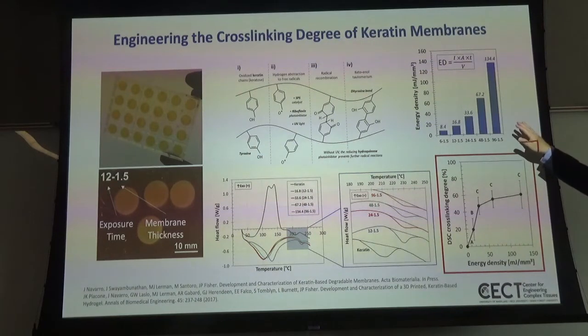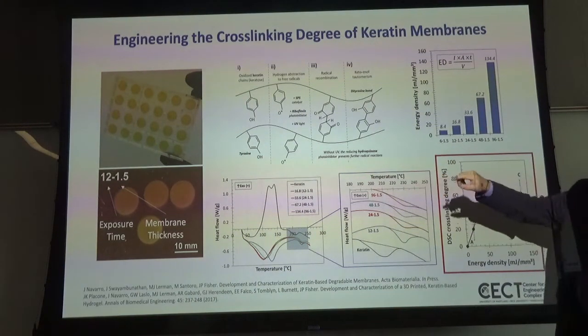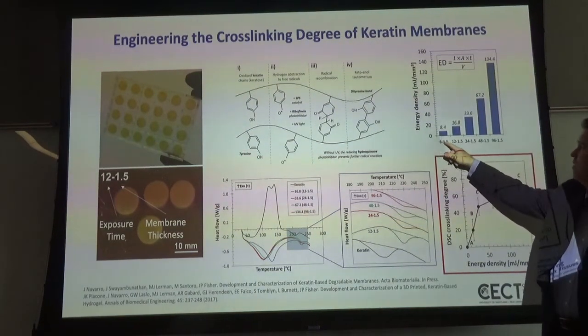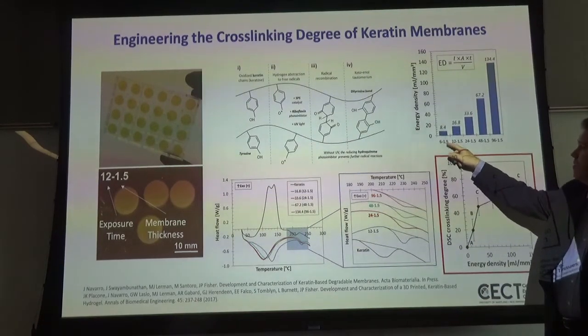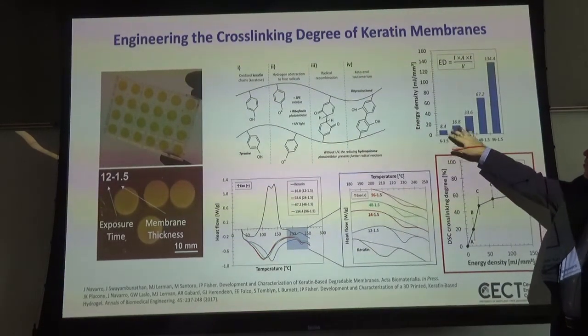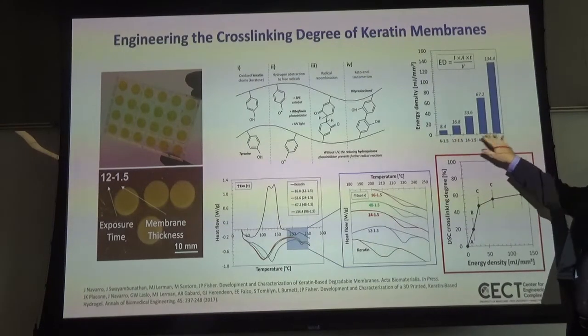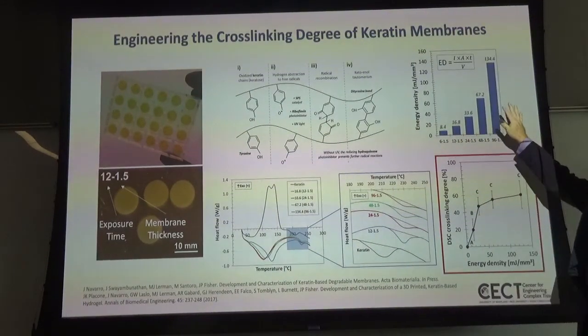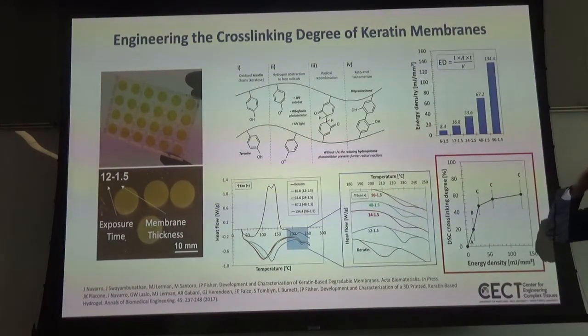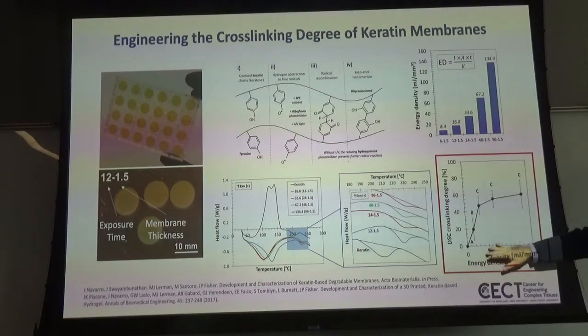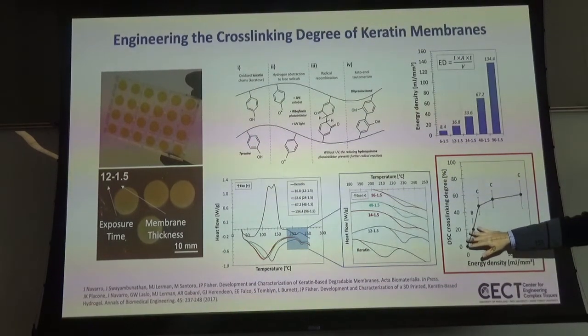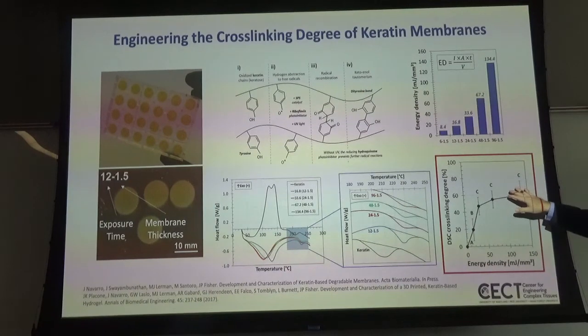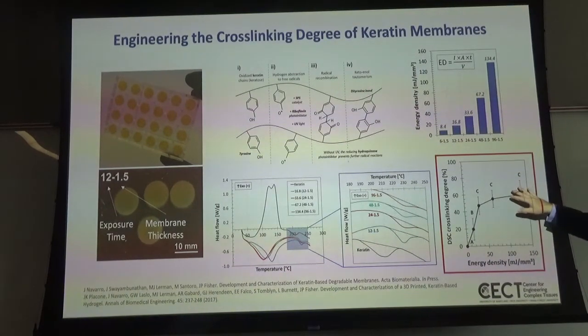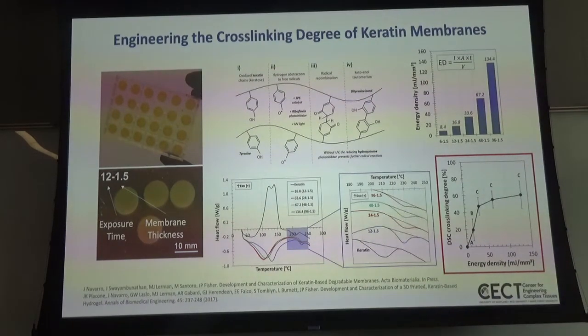So that's what's described here. So here are the two values. The first value is exposure time. The second value is membrane thickness. And we showed that by varying these two parameters, we could vary the amount of energy that was delivered during the cross-linking reaction, and roughly energy then correlated to cross-linking of the keratin by the riboflavin chemistry with these different energy density deliveries.